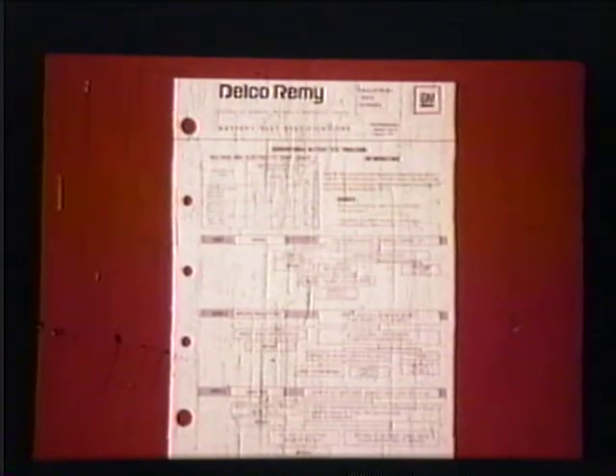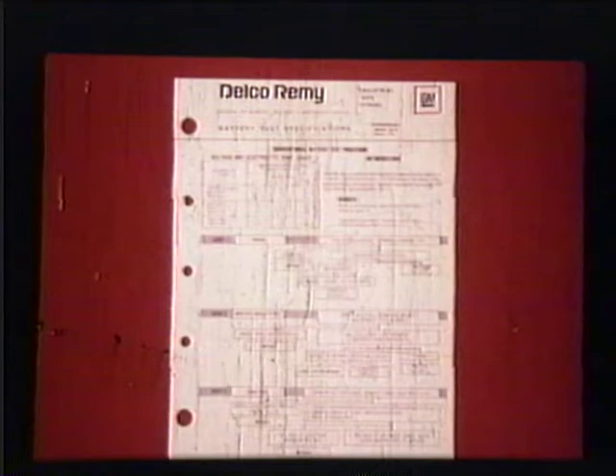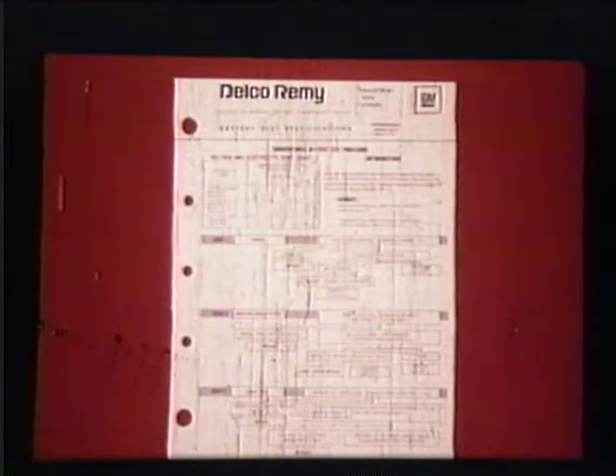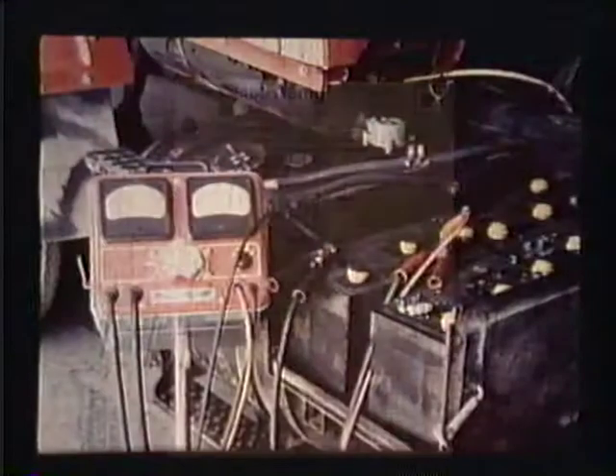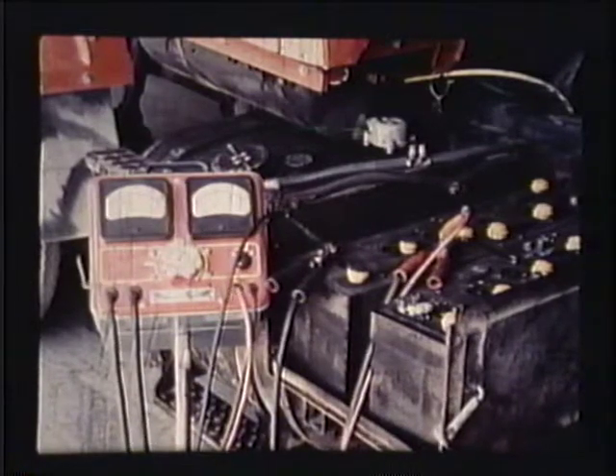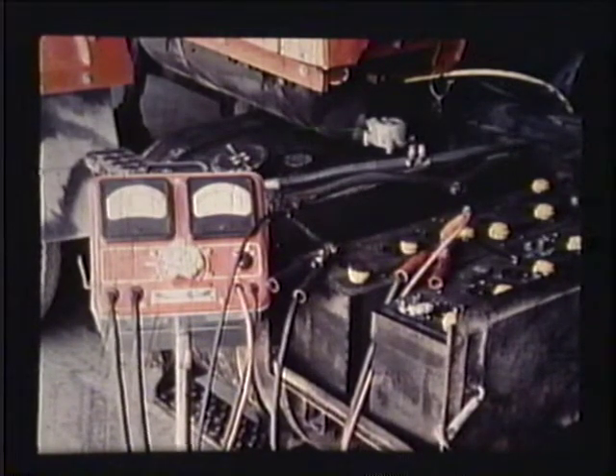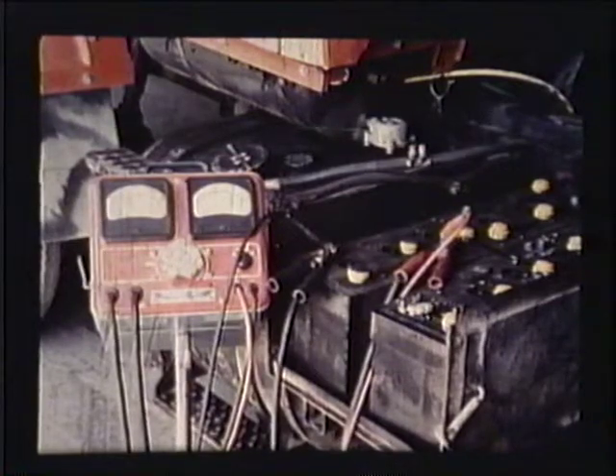Since we are testing a Group 4 6-volt battery, the load we are after is 450 amperes. Apply the 450 ampere load for 15 seconds and observe the voltage. At the end of 15 seconds, the voltage reading should be holding steady at or above 4.8 volts.